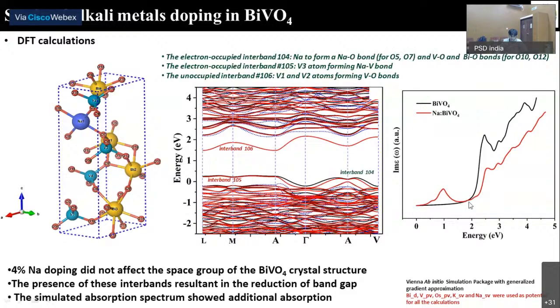That shows that our enhancement in the absorption might be due to formation of these interbands, which further helps in improvement in absorption. And with this, the calculated band gap also shows that there is a reduction in band gap. So the formation of these interbands and the reduction in band gap is the reason for the extra absorption that we are seeing in our experimental results.